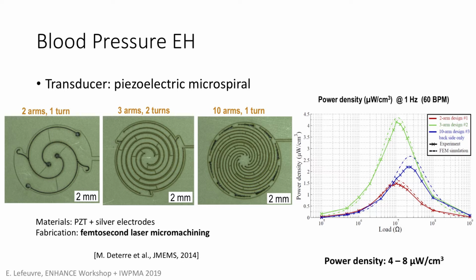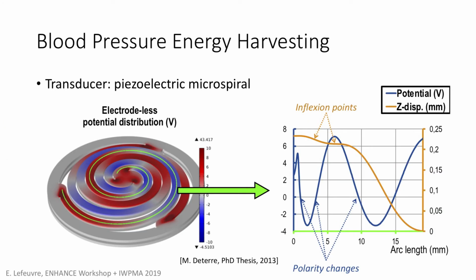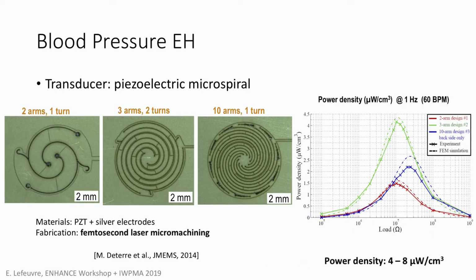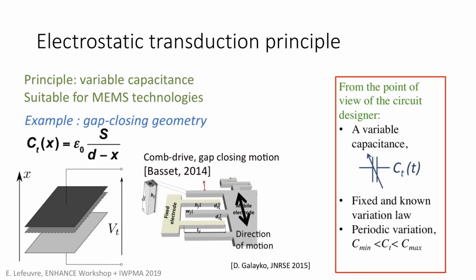We concluded that finally the problem is that our simulations showed that the polarity change of the voltage is very sensitive. If I come back to this slide, the polarity changes are very sensitive to the actual dimensions of the device. In simulation, we could see that. So our hypothesis is that we designed the electrodes based on simulations, but the devices we had do not behave like the simulations. So that's why the results are so low. But we were not totally disappointed, and we moved to other transducers. So we moved to electrostatic ones. And maybe, I'm not sure you are all familiar with electrostatic transduction, so maybe I should give you some basics on that.